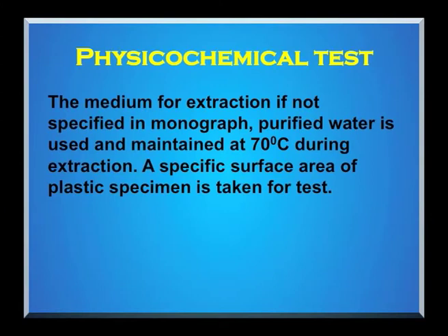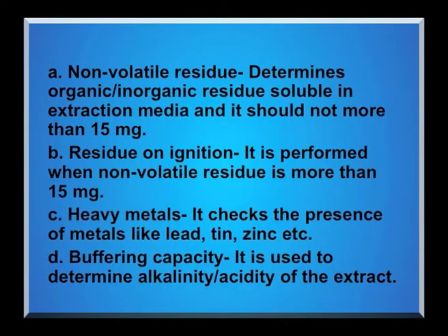The medium for extraction, if not specified in the monograph, is preferably purified water, maintained at 70 degrees centigrade during extraction. A specific surface area of the plastic specimen is taken for the test, and after extraction, the following checks are carried out. The first one is non-volatile residue. It determines organic or inorganic residue soluble in the extraction media, and it should not be more than 15 mg.